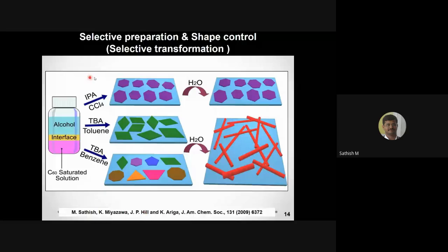So more interestingly, if I make this interface and make the hexagonal sheets, the rhombohedral sheets, or the mixture of sheets, and I disperse these sheets over water, these sheets are very stable. Whereas the sheets made with tertiary butyl alcohol, when I put them over water, undergo a deformation and are converted completely into nanorods, not rolled sheets. These rods are not rolled sheets, they are completely nanorods. Actually, I am sorry, I don't have a detailed presentation of this particular study. If some of you are interested, you can go to this paper and find out more details about how this deforms into nanorods over time when you just put the sheets over the water.